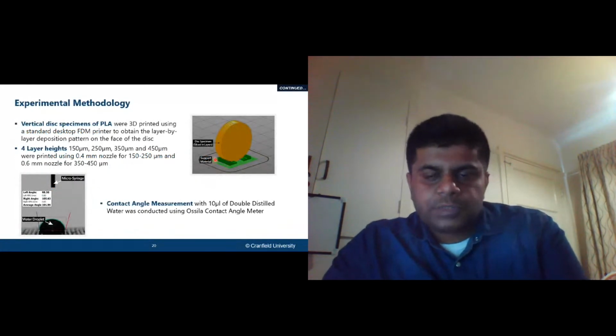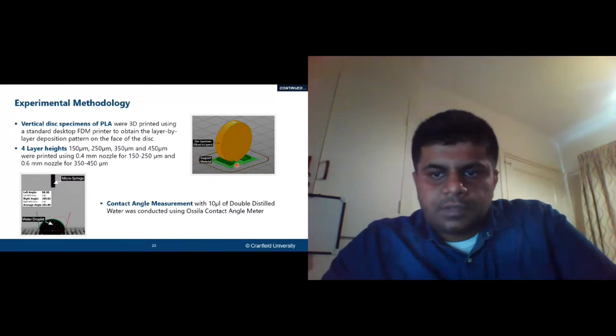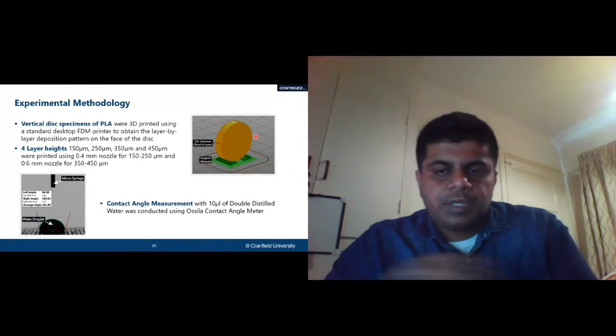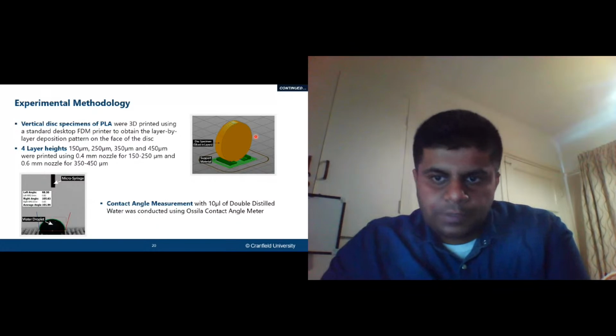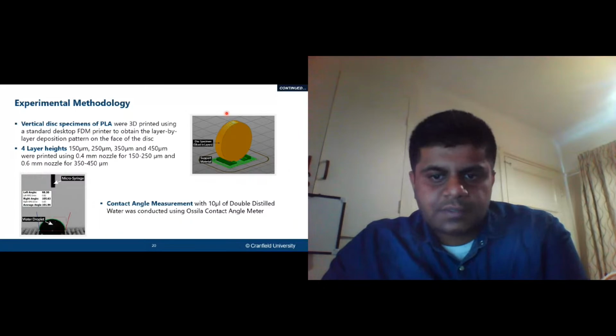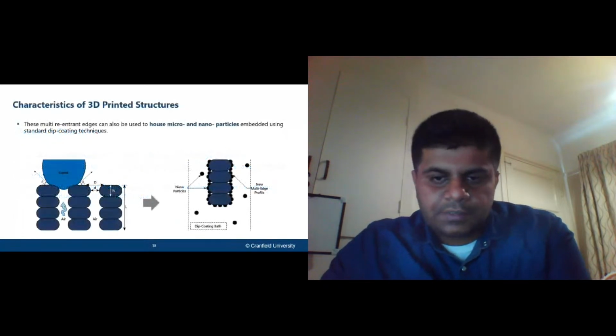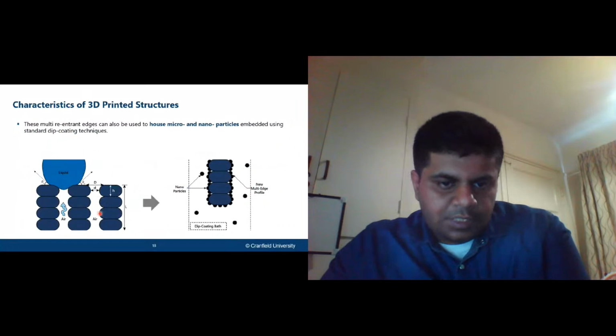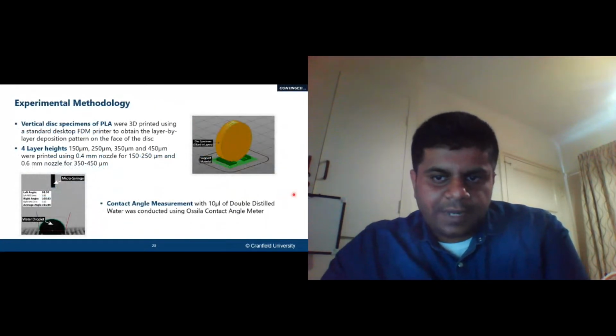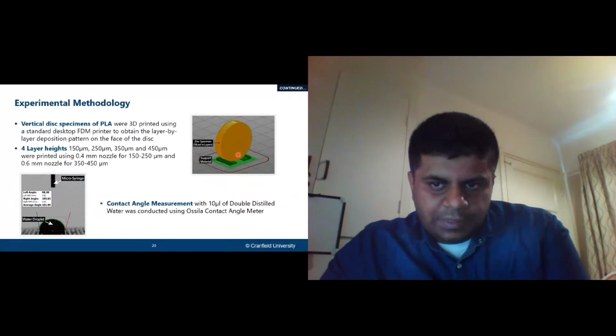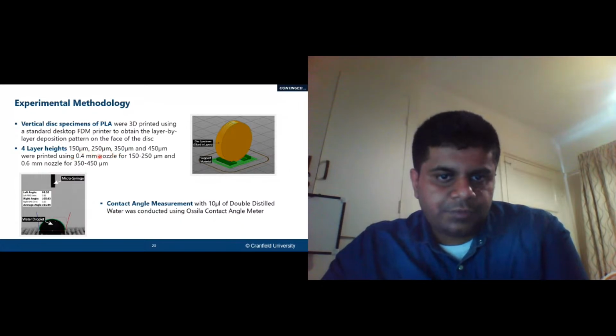So the steps we followed for this one: our choice of using a disk specimen was because we are investigating tribological wear, and the particular equipment only uses disks for investigation. So at the end of the day, we wanted to use a disk specimen. And obviously, I mentioned that our interest is to investigate these semicircular edges. So instead of printing it flat, we printed it vertically so that these edges are all translated onto the side of the specimen itself. So we chose 4 layer heights: 150, 250, 350, and 450.